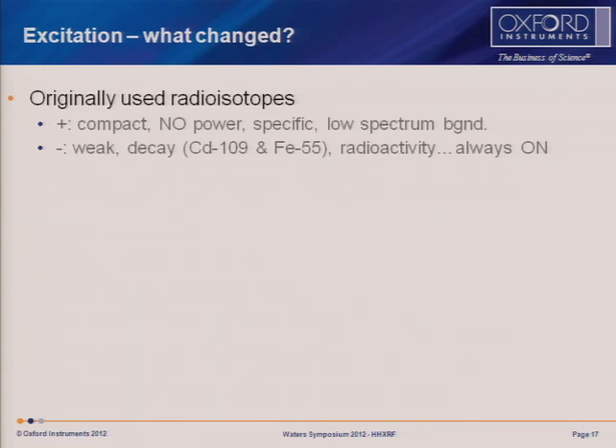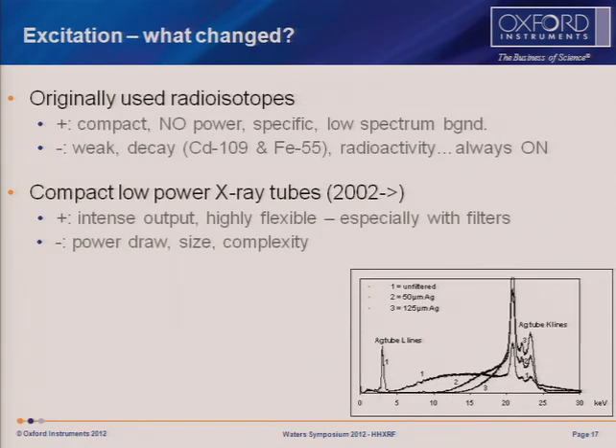However, they're generally weak unless you're brave and you want a very big source in there. And they all pretty much decay. Cadmium 109 and Fe-55 in particular, which are the favorites for stainless steel analysis, they're also always on and radioactive. People don't like them. So X-ray tubes come along, they have a much more intense output, and they're highly flexible. The spectrum down here shows the output spectrum, keV along here, of 3 different filters. And you can see the quite different shape of the excitation spectrum that you can gain by the simple use of beam filters. So very intense, but they require power.